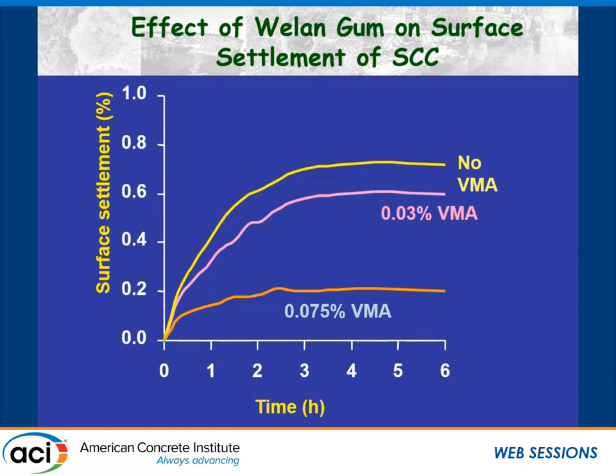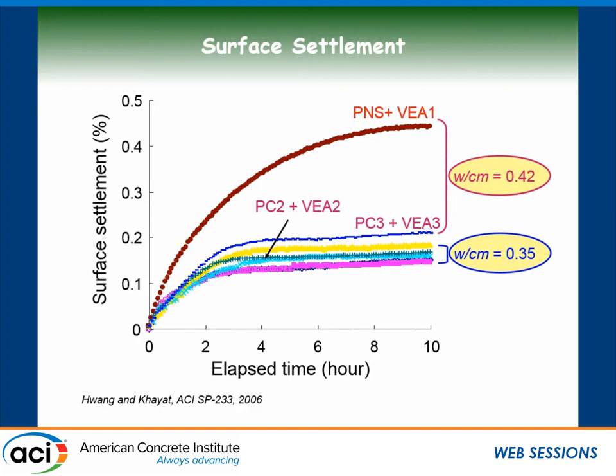So again, there are two approaches to proportioning SCC to ensure static stability. Either lower the water cement ratio, and here we see that reduction of water cement ratio, 0.42 to 0.35, would reduce surface settlement, or use 0.42 but also build up viscosity by using viscosity enhancing agents. Regardless, you can get SCC mixtures that are very stable.